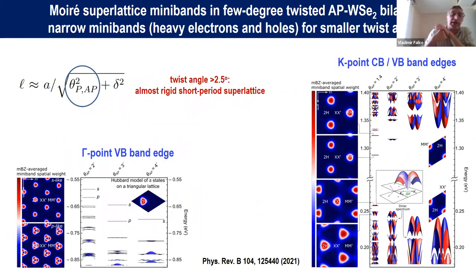Also, if you start playing with the same chalcogen, basically with homobilayers like tungsten diselenide bilayers, but now twisting the angle, going from higher misalignment to lower misalignments, one can also look at those minibands. They would appear both for the conduction band and valence band. One would have to be very careful what to discuss in terms of relevant electronic properties. For example, for absorption, it would be necessary to look at what happens at the K points of the Brillouin zone. For discussing the electric transport properties of p- or n-doped material, one would have to understand where the actual band edges are. And due to the interlayer hybridization, the gamma point is promoted very strongly in the TMD.